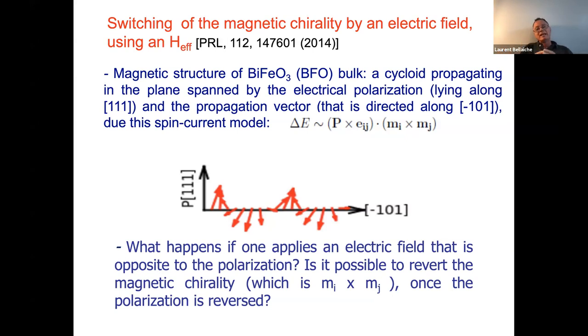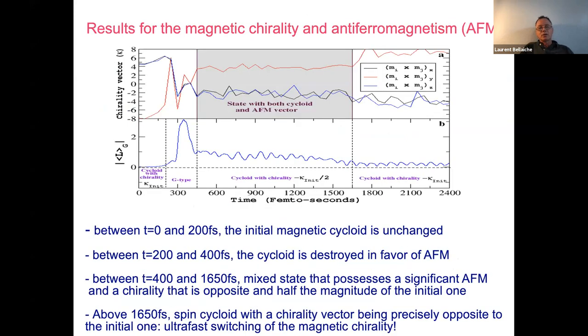This means, physically speaking, that if you change the direction of polarization by applying the electric field, you should change the magnetic chirality. So we tried that in this paper, probably in 2014, this PRL paper. This is the magnetic chirality versus time, and this on the bottom is the AFM vector, antiferromagnetic, versus time. What these pictures are telling you is that between 0 and 200 femtoseconds, the magnetic cycloid is unchanged. Between 200 and 400, it is destroyed in favor of the antiferromagnetic state.